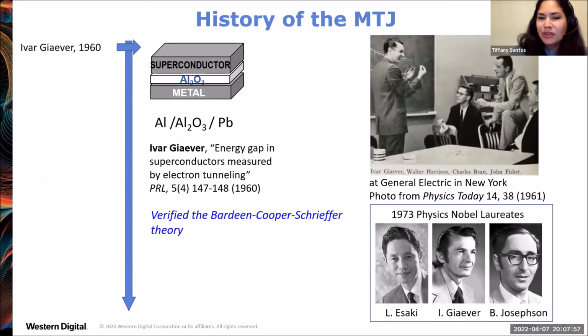So a great place to start telling the history of the magnetic tunnel junction is with Ivar Giaever. He was in New York working for General Electric as a mechanical engineer in the late 1950s, and he wanted to study conductance between metals. So he came up with the idea of using an aluminum electrode and then using its natural oxide at the surface, aluminum oxide, as a tunnel barrier. And then he had the idea of putting a lead counter electrode, it's a superconductor, and using this tunnel junction structure, he showed the energy gap in superconductors measured by electron tunneling coming from the aluminum. So this was a remarkable verification of the BCS theory, and for this, he received the Physics Nobel Prize in 1973.